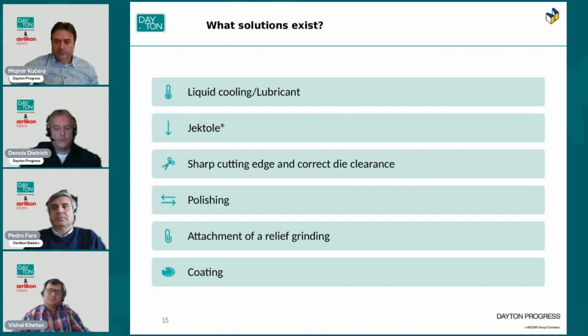Lubrication is reducing the friction between punch and the aluminium and also reducing heat in this operation. But this acts as a bonding agent between the punch and the slug. This magnifies surface tension and increases the possibility of slug bonding and pulling. To avoid this, Jektole punches will be a great help. The benefits of using a Jektole punch are twofold.